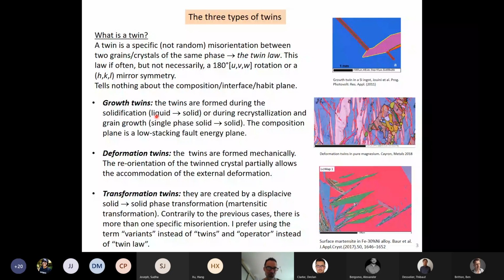The growth twins are formed during solidification, during the liquid to solid transformation. The solid can appear with some defects, and these non-random defects are actually the twins. Or they can also appear during recrystallization or grain growth. In that case, during grain growth, some accident can happen, but because of the low stacking fault energy, it's not random.